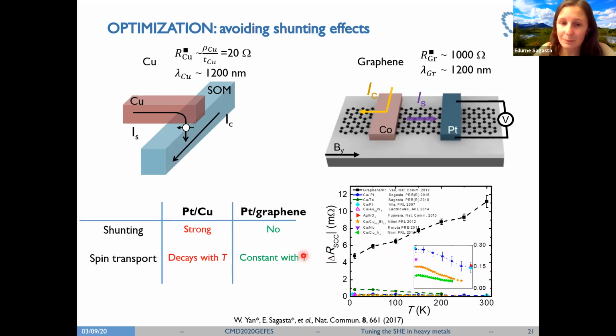In case of graphene, the spin diffusion length is constant. So we should expect a constant signal. However, we know that the spin to charge conversion signal is proportional to the spin Hall angle and to the resistivity. And both are increased when the temperature is increased. Therefore, we see this increase in the signal of the spin to charge conversion. So in the end, due to all these factors, what we have been able is to enhance almost 2 orders of magnitude, almost 70 times, the spin to charge conversion signal that is useful for applications at room temperature.